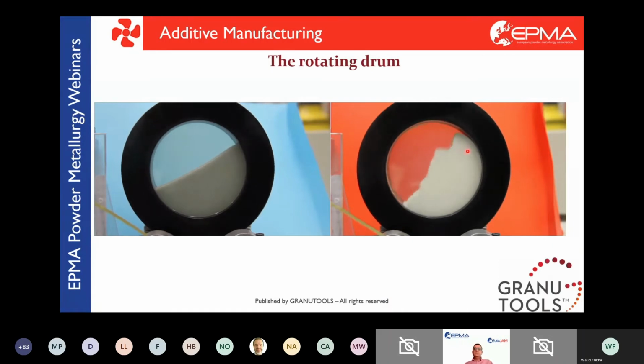On the right side, when the grain reaches a height that is too high, it cannot flow on its own because it's sticking to the rest of the powder, so it cannot fall freely. It needs to wait to reach a critical mass, and the amount of powder needed to detach one block will depend on the forces connecting the grains to each other. If the powder is highly cohesive, it will need a lot of mass to break. If it's not cohesive, each grain can break separately and create a flow.